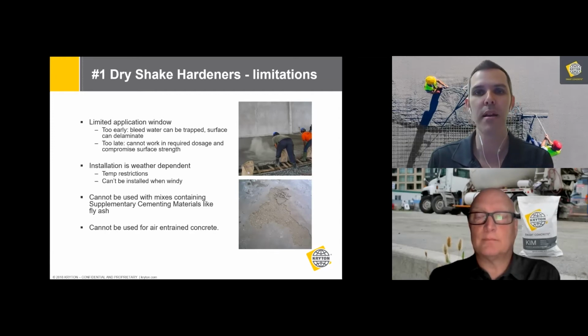They're also going to be battling wind. If it's windy, this dry shake is going to be blowing all over the job site. You can't get it uniformly applied over your slab. Often they have to put the roof on their structures first before they cast their slab, so this can really affect the schedule that they're trying to work with. And they also can't be applied over air-entrained concrete, because the troweling needed to work them in can cause delamination when you apply that troweling over air-entrained concrete. So there's a lot that they have to deal with.